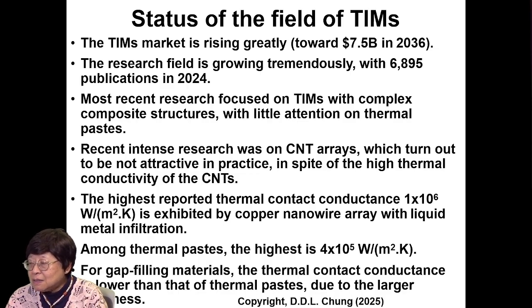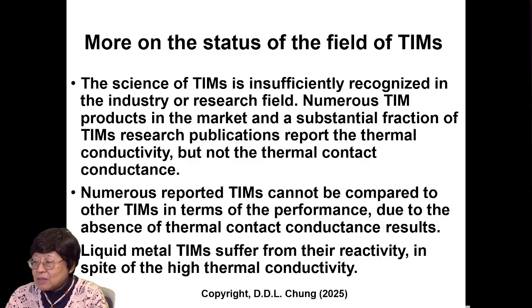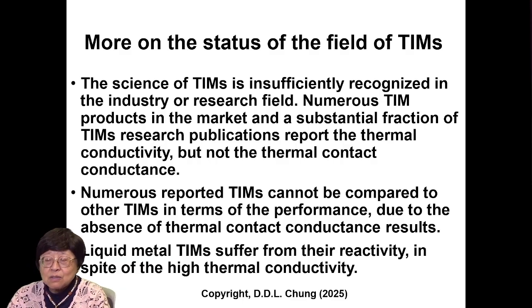The highest reported thermal contact conductance, 1 × 10⁶ watts per meter square K, is exhibited by copper nanowire array with liquid metal infiltration. Among thermal pastes, the highest is 4 × 10⁵ watts per meter square K. For gap-filling materials, the thermal contact conductance is lower than that of thermal pastes due to the larger thickness. The science of TIMs is insufficiently recognized in the industry or research field. Numerous TIM products in the market and a substantial fraction of TIMs research publications report the thermal conductivity, but not the thermal contact conductance. Numerous reported TIMs cannot be compared to other TIMs in terms of the performance due to the absence of thermal contact conductance results.